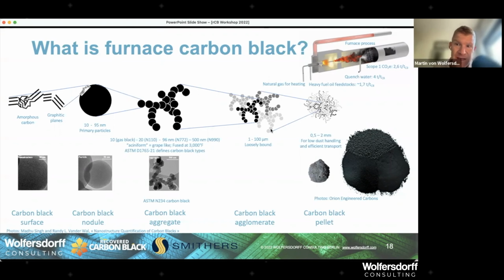And that is really a good value, because if we don't treat the gas that is separated from the carbon black and get rid of the methane, it would be closer to 5 tons carbon dioxide per ton of carbon black.